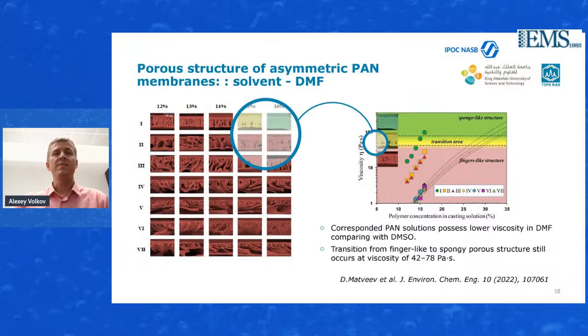structure, because the NIPS process depends on the diffusion of the components from the polymeric solution phase to the non-solvent phase and also vice versa. And the higher viscosity of the polymeric solution might hinder that diffusion and make it a more uniform phase separation, avoiding the penetration of the liquid phase into the polymeric solution, which forms the finger-like structure.